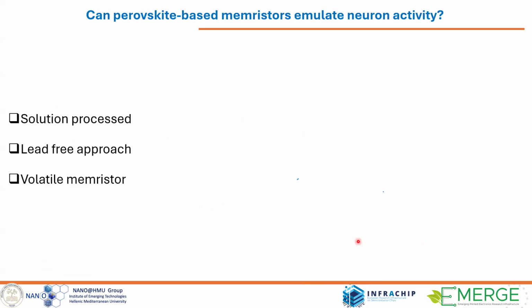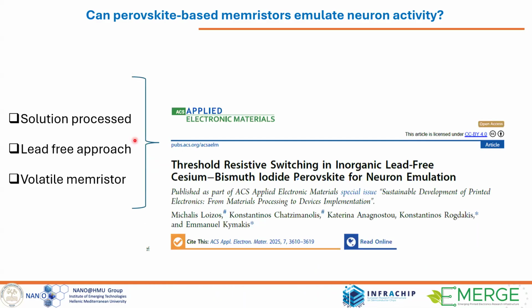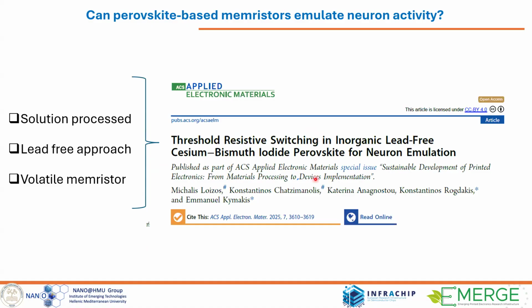Now, I showed you a lot of results on non-volatile memristors for synapses. What about neuron emulation? For this, we need a volatile memristor. So I decided to change the formulation to remove lead from our system and to move to a lead-free configuration. This led to the first publication for our group a few months ago. We demonstrated volatile switching, or threshold resistive switching, using inorganic lead-free perovskites based on cesium and bismuth. I will show you later. And then using these volatile memristors to demonstrate some protocols for neuron activity.